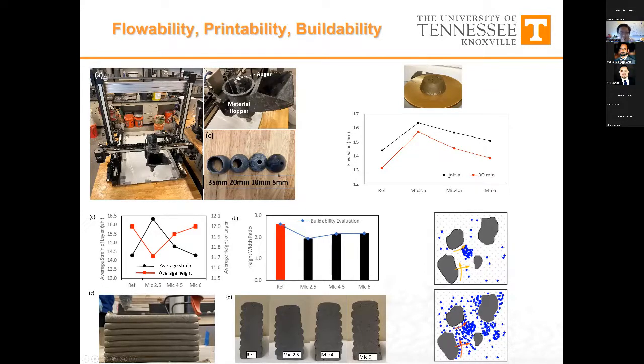One thing that we find pretty interesting is that at the lower loading level of those functional particles, the flowability actually goes up before it slowly comes down. And that is verified by the buildability test, where we can see that with a lower dosage of PCM particles in the cementitious system, the buildability first increases because it's easier to flow, before it goes back down.